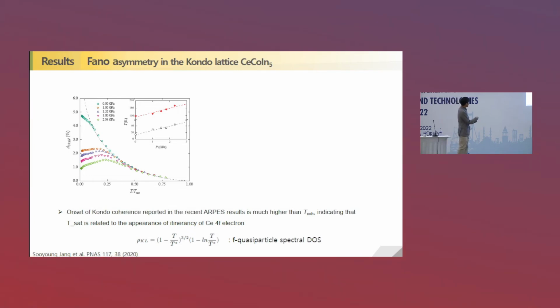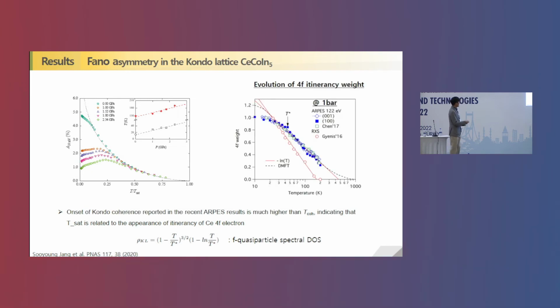Okay, and the inset shows the saturation temperature, the red dot. At ambient pressure it is 150 Kelvin to 180 Kelvin at high temperature. Note that this temperature is much higher than the so-called coherence temperature. This has already been reported in ARPES measurements, where they obtained the itinerant f-weight. They started not at the coherence temperature, but at a much higher temperature, which in some sense is consistent with our result that the asymmetry comes from the itinerancy of electrons.